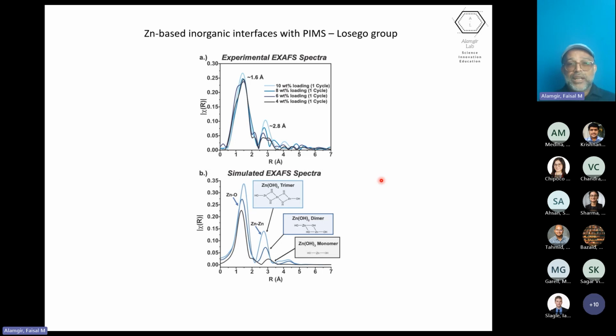So think, a close analogy would be a host system, like growing inorganic materials inside of the walls of a host. So one of the things that we were able to do using this instrument is we were able to show that there's kind of a polymerization, a mini polymerization type of reaction that's happening in the zinc-centered inorganic materials as they are growing onto and linking to the polymer matrix. But this is from zinc. Zinc is something we can do with our instrument that we currently have.